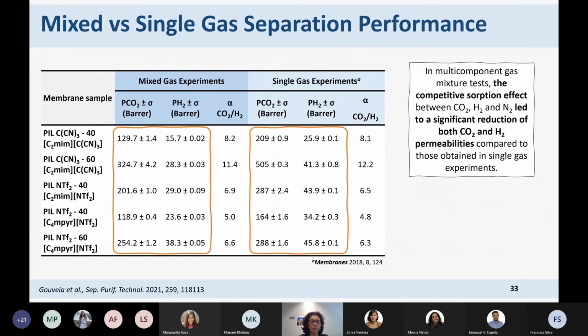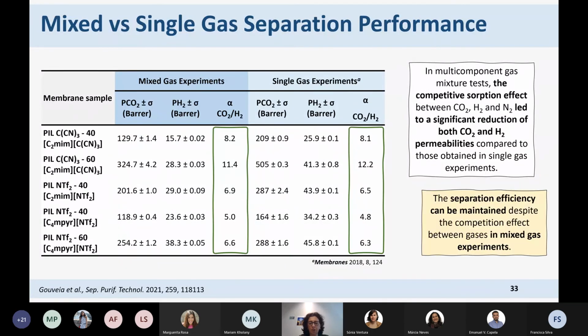And what we can see from here is that in multi-component gas mixtures, we have a significant reduction in both the permeability of CO2 and H2. As you can see here, it changes from 129 to 209 and from 15 to 25. And so that is maybe because they are competing with each other.